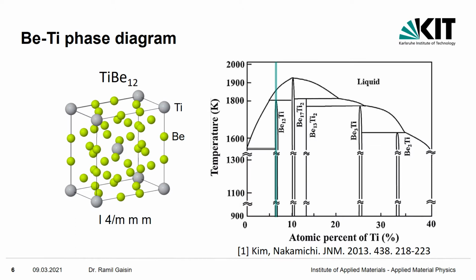The problem stems from the fact that titanium beryllide is a very hard and brittle material, comparable to gemstones. It has a complicated crystal structure with a limited number of slip systems, and its manufacture has faced many challenges. For example, conventional casting results in higher porosity and compositional shift due to peritectic reactions here. That is why we focused on the powder metallurgy route.